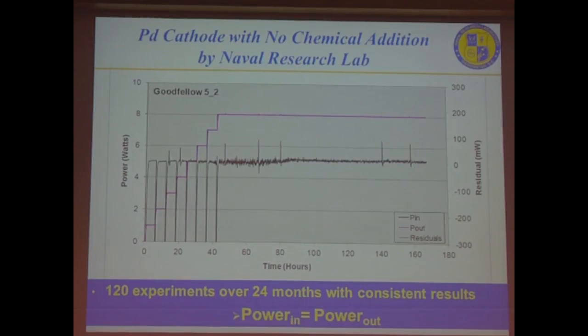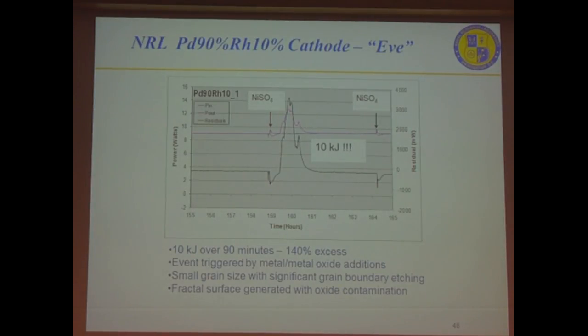NRL got into the picture, as you saw on the chronological scale of time, and they were conducting 120 experiments with 0 results. By the way, one of the reasons is they were running experiments of 1 week. So sometimes it's too short to see what's going on. So in order to accelerate the process, they started adding by injection NiSO4 and other ingredients into the solution, into the electrolyte. Why did they do it? They believed that it would precipitate on the surface and create this morphology. And in fact, they analyzed it after that, and they saw this typical morphology, and they started seeing excess heat.